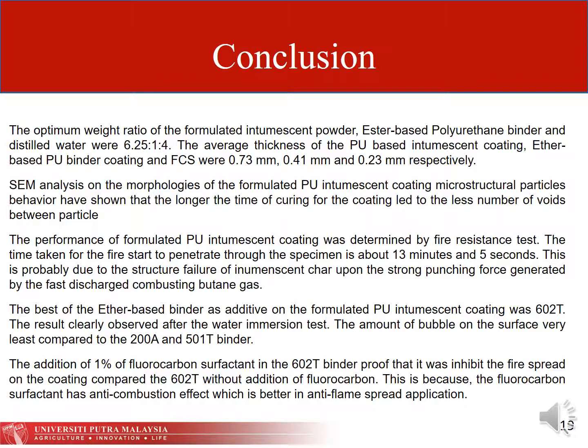501T binder. The addition of 1% of fluorocarbon surfactant in the 602T binder proved that it inhibits the fire spread on the coating compared to the 602T without the addition of fluorocarbon. This is because the fluorocarbon surfactant has an anti-combustion effect, which is better in anti-flame spread application.